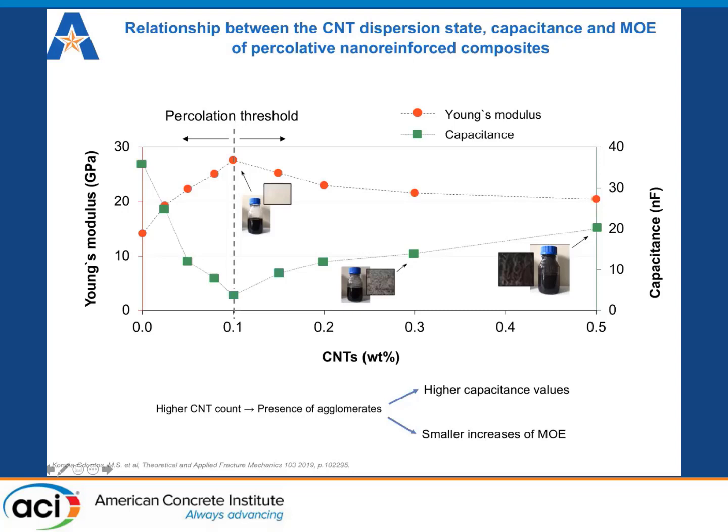So, we cannot ever claim that a perfect dispersion really exists. A few small-sized CNT agglomerates that are capable of storing the electrical charge are probably present. Hence, some low values of both capacitance and resistivity are observed.